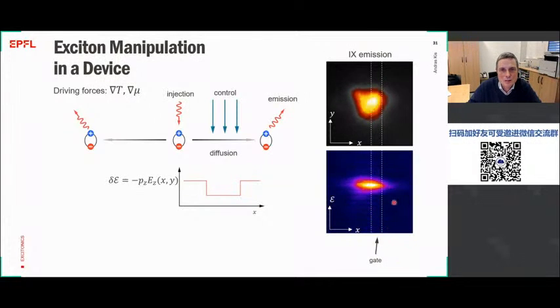And here on this series of images, which correspond to actual data, you can see in the top a map of the exciton cloud and how it's spreading out as you're changing the intensity. It's also here reaching this region of the device where we apply an electric voltage. And what happens is that you see as the cloud reaches this potential dip, it somehow gets attracted into it.